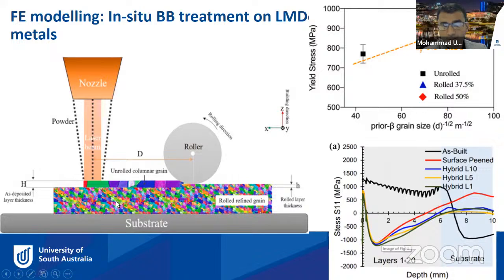As you can see here, the grain was a bit coarse after the laser cladding, but next to the cladding, if you have a roller ball burnishing doing the treatment instantly in situ, then you can see that you make the grain much finer, and fine grain basically means better mechanical properties. This can be evident from this picture, as you can see here. So you can improve the mechanical properties like the yield stress, as well as create some compressive stress in the subsurface as well.